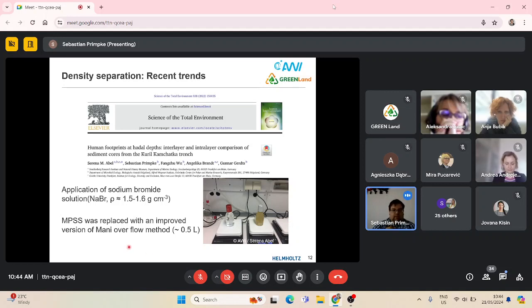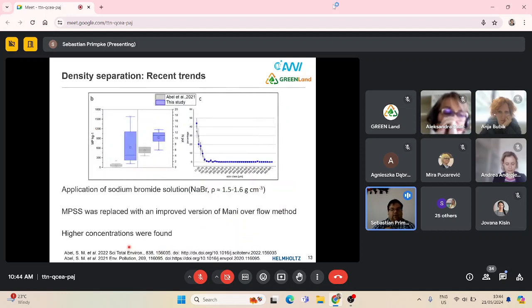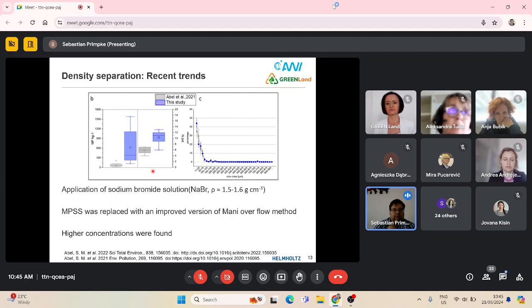But also the results we find have a higher number of smaller-sized microplastics. So if we compare the same samples of the same area, taken with the same sampling crews, we found that we have higher numbers of microplastics, but also higher polymer diversity. So using these smaller-sized sampling devices was extremely efficient. It also allowed us to analyze the layers of the different cores which were taken. So it was extremely useful. For example, we now teach this method within the GREENLand project because it's easy to transfer to other laboratories due to the easily available devices.